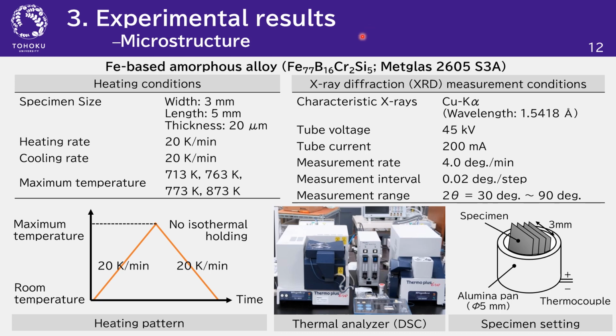The sample was cut into pieces 3 mm wide and 5 mm long and set in an alumina pan like this. For heat treatment, the heating rate was set at 20 Kelvin per minute and the sample was cooled to room temperature at the cooling rate of 20 Kelvin per minute, without holding it at the maximum temperature. Structural analysis of the heated sample was performed using XRD and TEM observation.